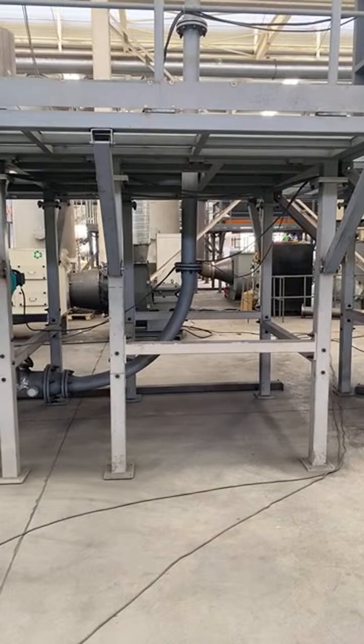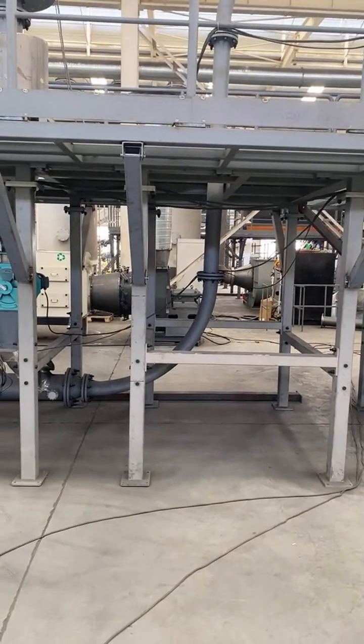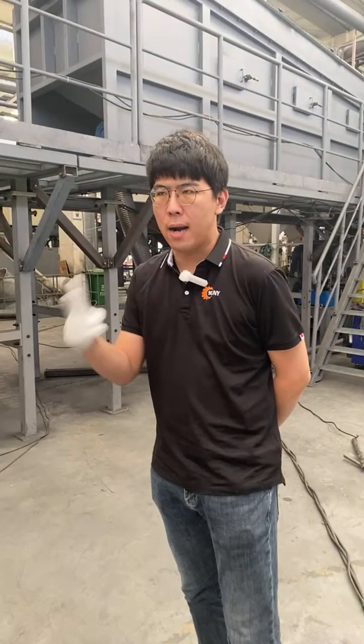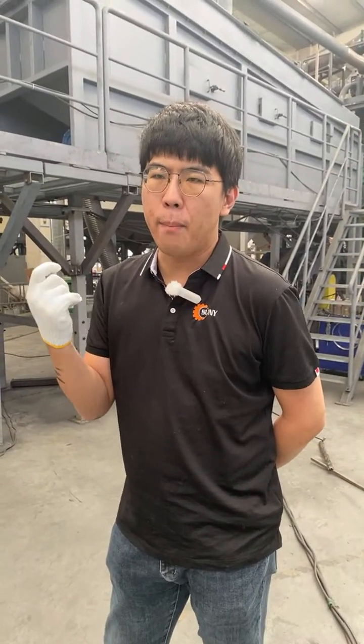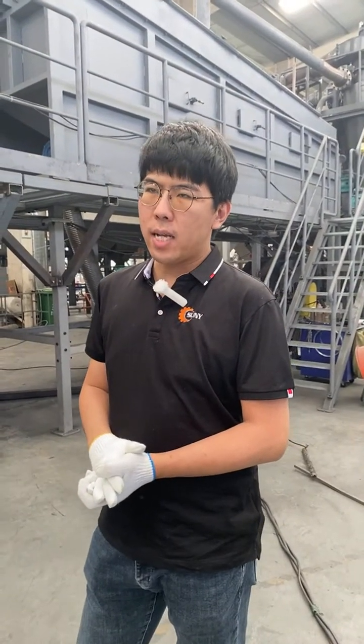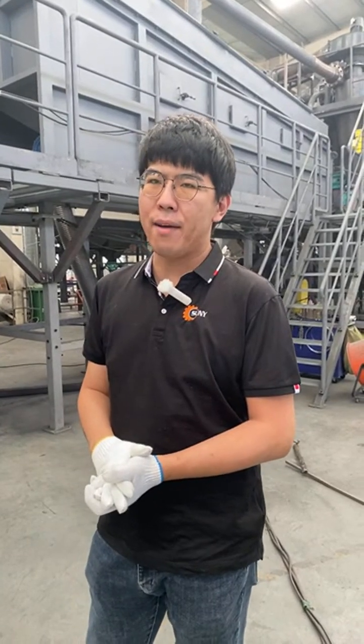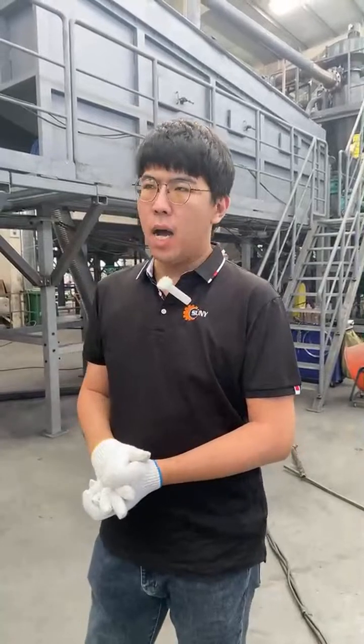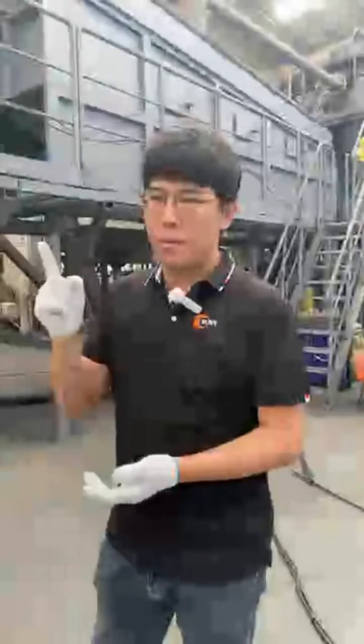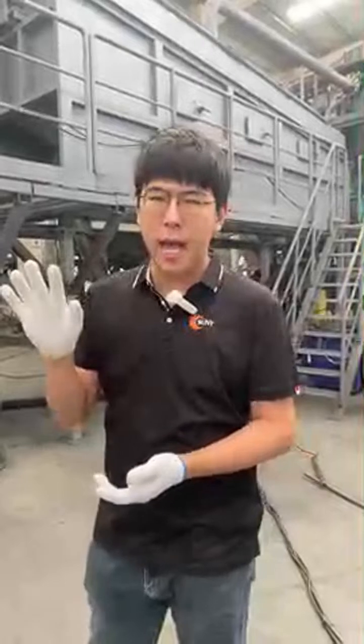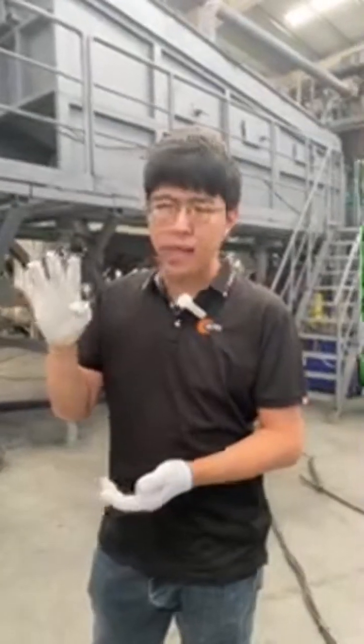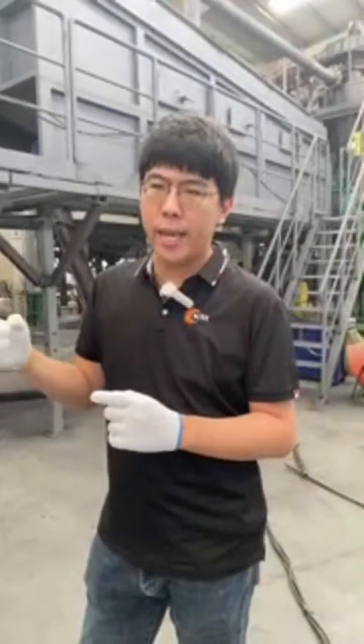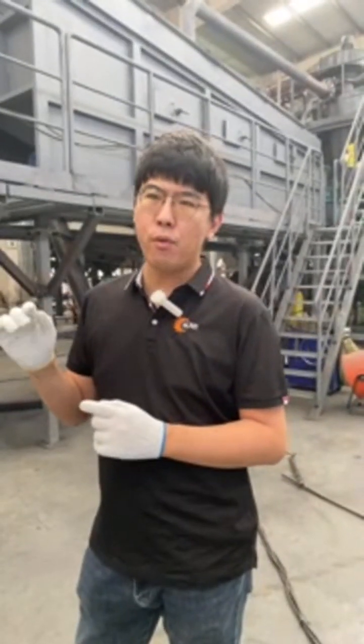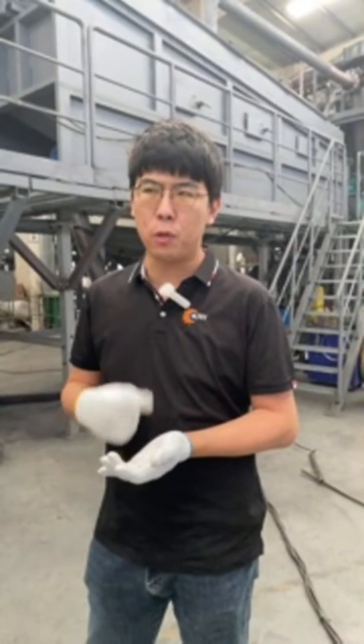Okay, thank you. Does that mean the machine for 110 black mass is of higher quality than the 500 kilograms per day one? The quality we can say from two parts. First part is recovery. The second part is black mass purity. Talking about the recovery, the black mass is bonded on the material, so you cannot recover all the black mass. 10 batteries have 500 kilograms of black mass. If you don't heat up, maybe you can only recover 400 kilograms. But after heat up, the adhesive will be destroyed. So through the rolling, shaking, and the crushing, you can remove all the black mass. So you can recover around 490 kilograms of black mass. So firstly, recovery will be around 5 to 7% higher.